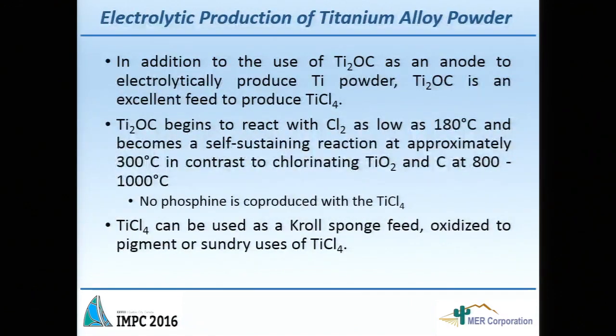So the very interesting thing about the Ti2OC is that it can be chlorinated at very low temperature, right? Because basically you're oxidizing it. It's already in the lower oxidation state, and when you put chlorine, it's an exothermic reaction. So you can produce TiCl4 at very low temperature. It starts at 180 degrees. At 300 degrees, it is a self-sustaining reaction. So it is also a way to produce TiCl4, and the TiCl4 can be used in the Kroll process to produce sponge, or you can use it for other application. Very, very unique material, the Ti2OC.